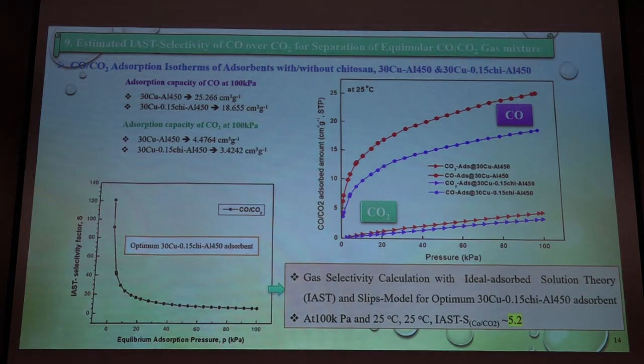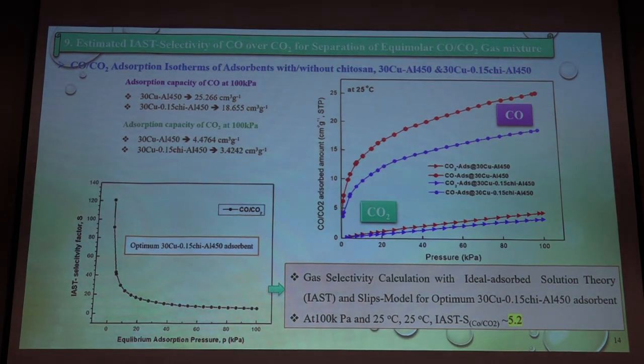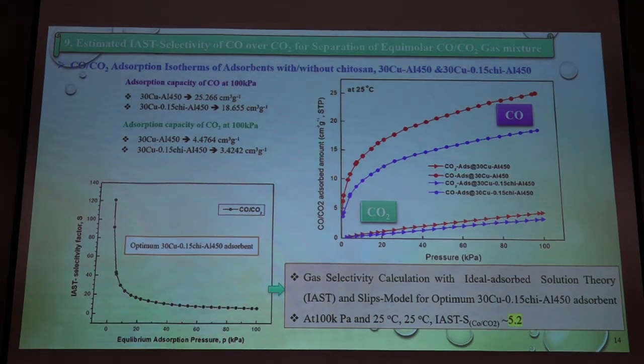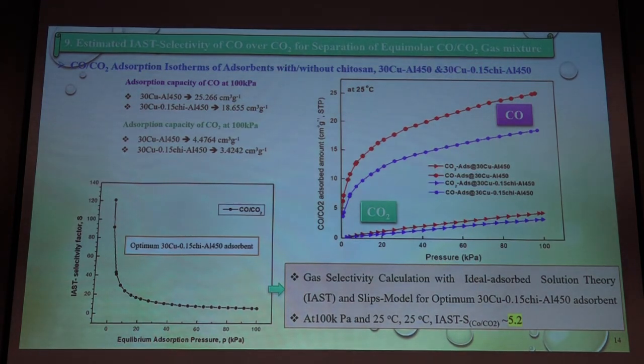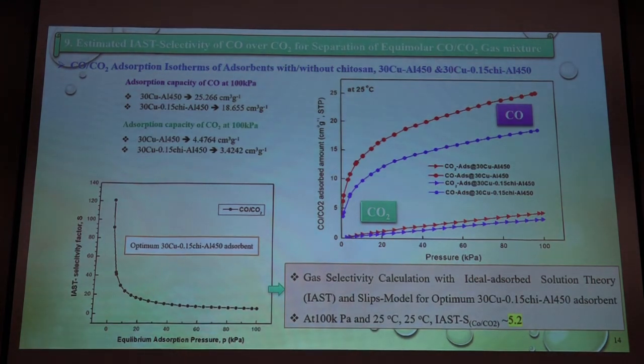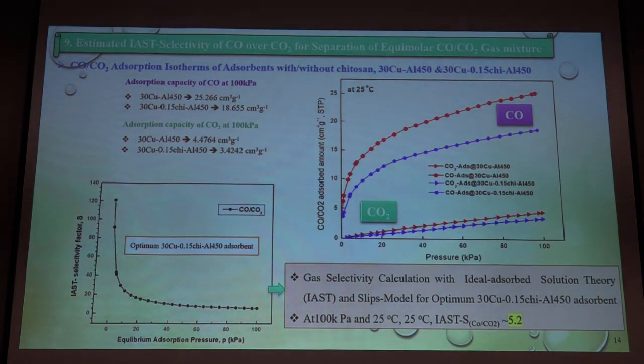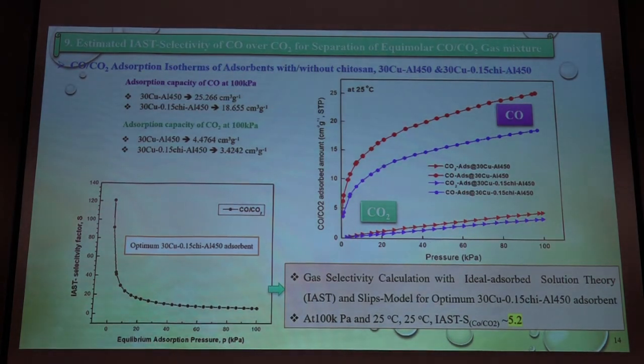This time I considered the separation of CO from CO2. Firstly, I estimated the CO selectivity factor after fitting the adsorption data with the model called the SIPS model, and then I used the ideal adsorbed solution theory. By combination of this model and this theory, I calculated the CO selectivity factor, and its value is quite acceptable to separate the CO from the CO2.